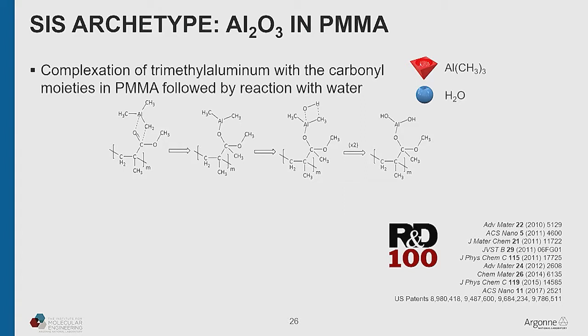So in this case, reactant A is trimethyl aluminum, and reactant B is just water. And the carbonyl groups are the primary affinity site in PMMA for trimethyl aluminum. So that'll bind in a way that we've actually spent a long time analyzing with in situ infrared spectroscopy and so on. And then water will come in and complete the reaction and grow aluminum oxide.